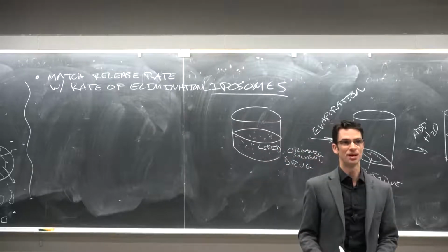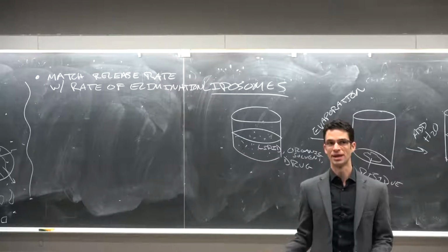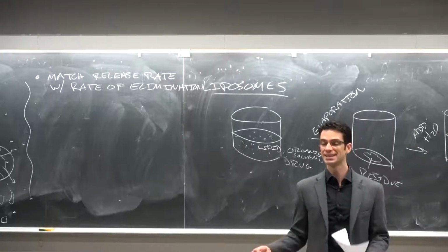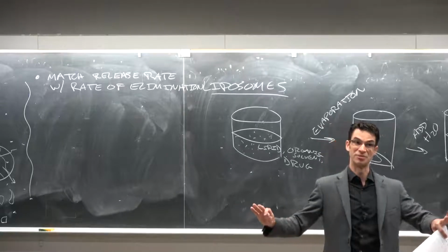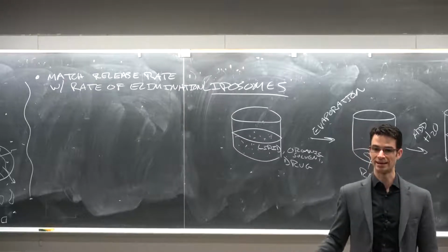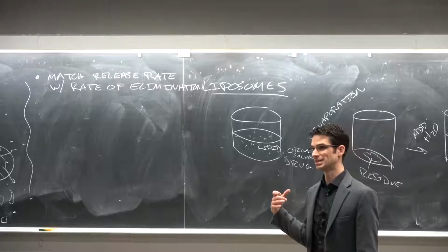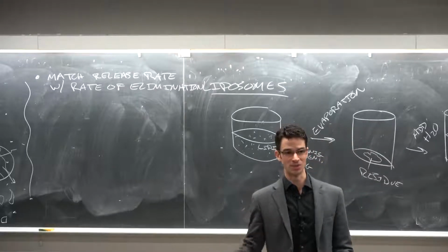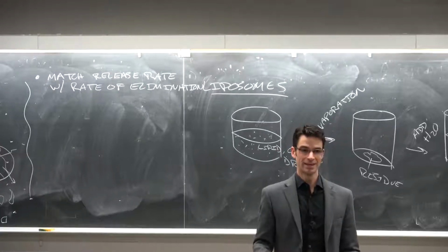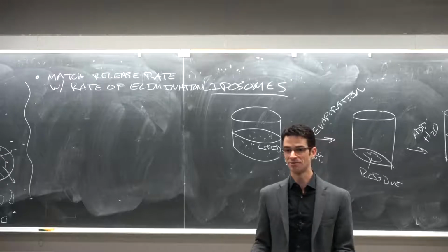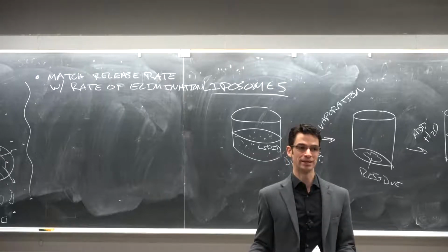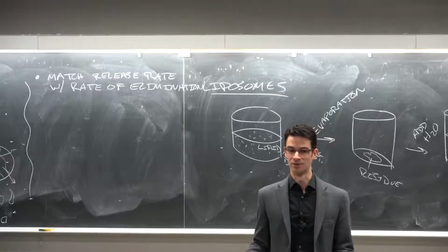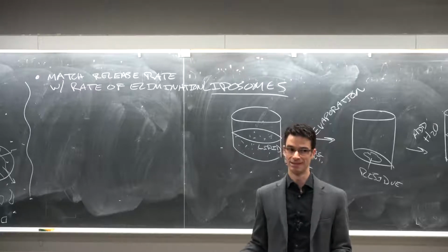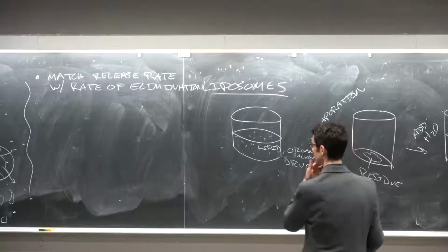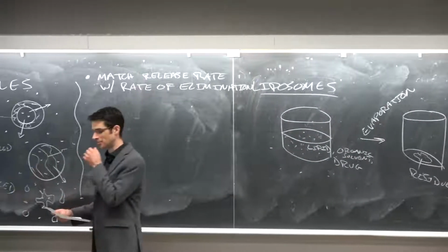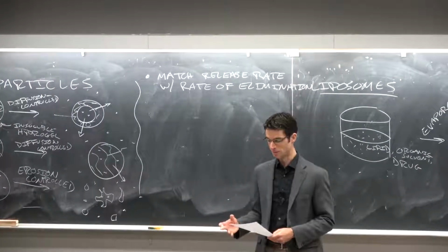In some cases, you have particles that are larger, and depending on the surface chemistry, and there's a big field here, you can actually have them degraded in the liver and sent to the gallbladder to be eliminated as bile. But unfortunately, for insoluble particles, a very common fate above 10 nanometers is to just get stuck in the liver or the spleen and never leave. And this is particularly the case for metallic nanoparticles, but insoluble polymer nanoparticles have this problem as well.